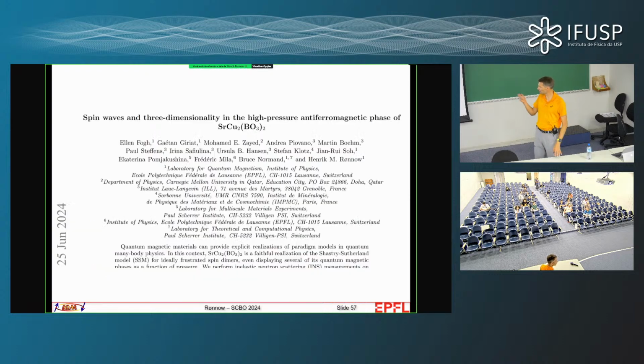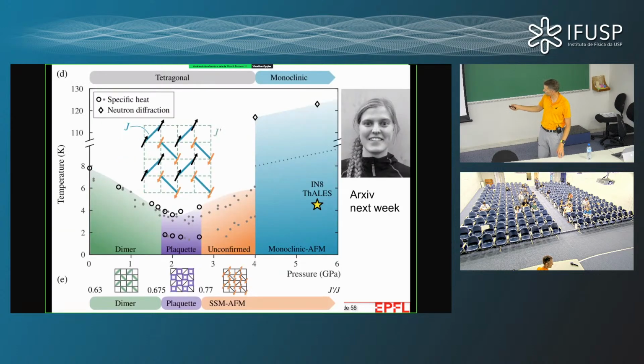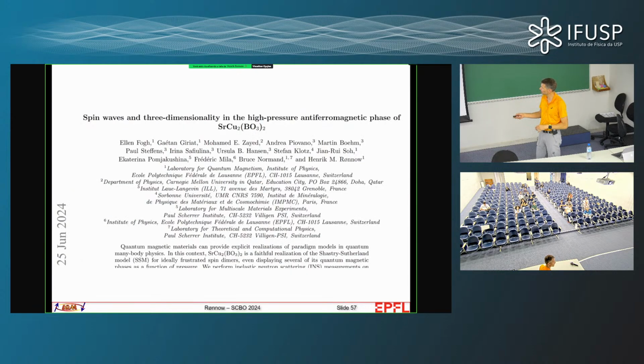Now, I then jumped to this experiment here, which you see is at high pressure. In fact, these are experiments performed at 5.5 gigapascal. This is actually using an anvil cell. It's not a diamond anvil cell because we need big samples. It's something called a Paris anvil cell, where we have tungsten carbide anvils, and the sample is on the order of tens of, maybe 20, 30 cubic millimeters. No, hang on, I'm wrong. Perhaps rather an 8 to 12 cubic millimeter sample, and then we can reach here. But again, to be able to measure excitations from there is not so easy, and we do not get as beautiful data as the one shown here.